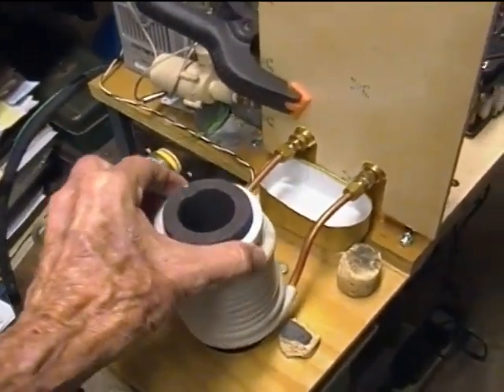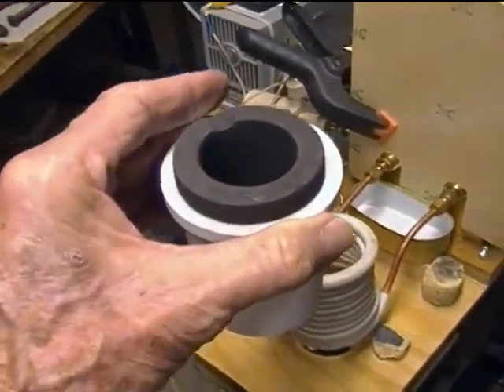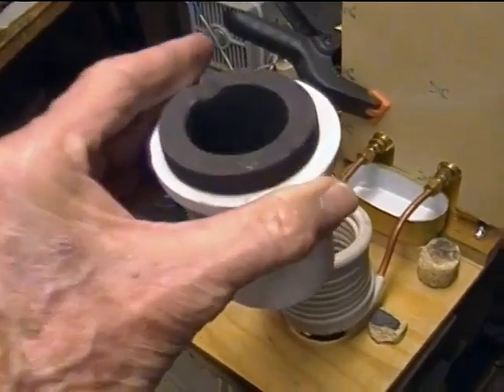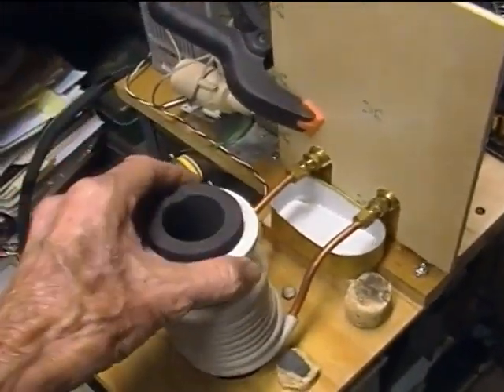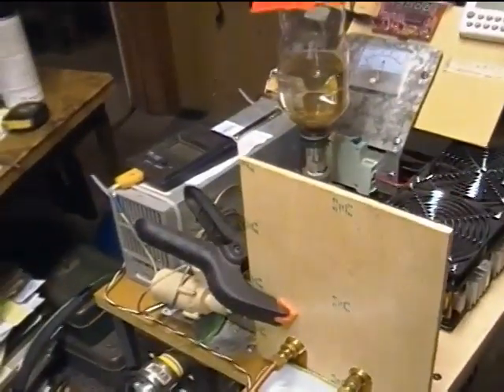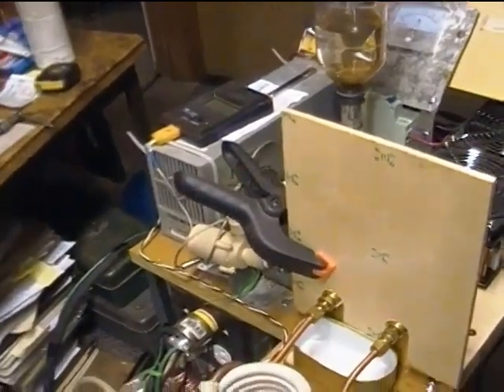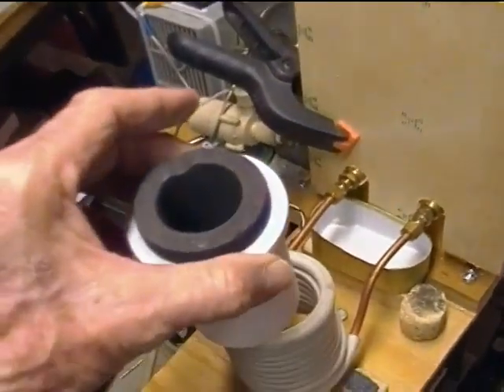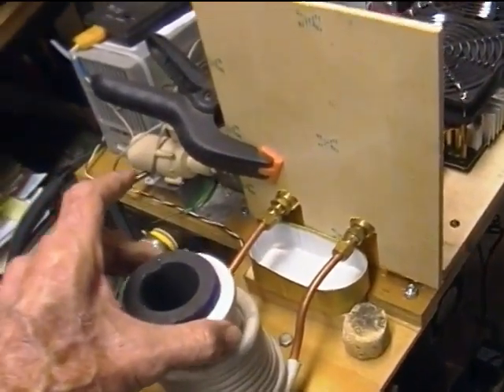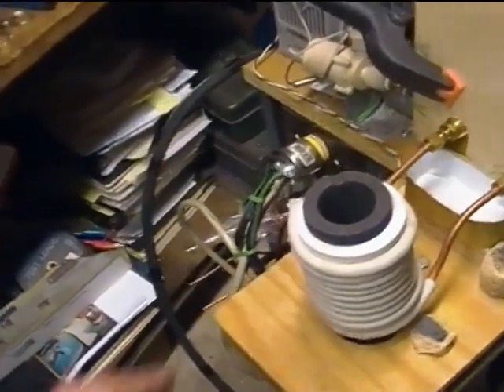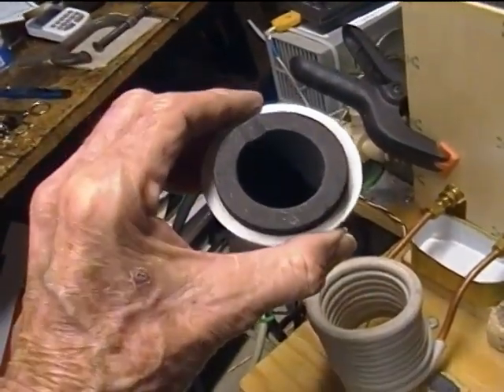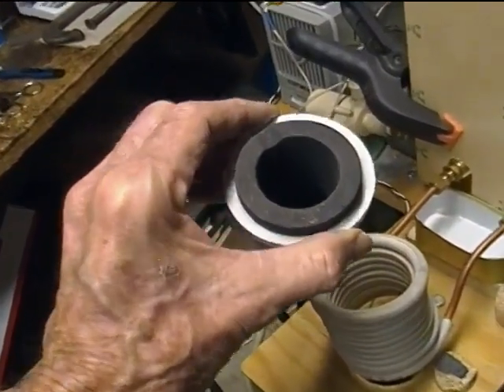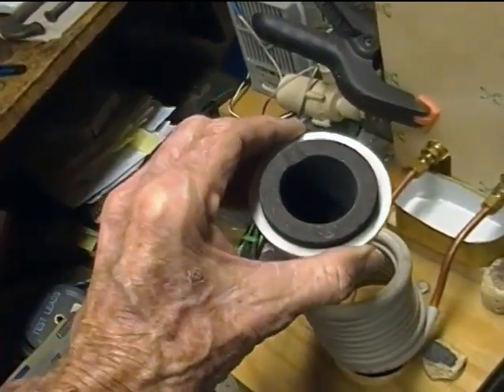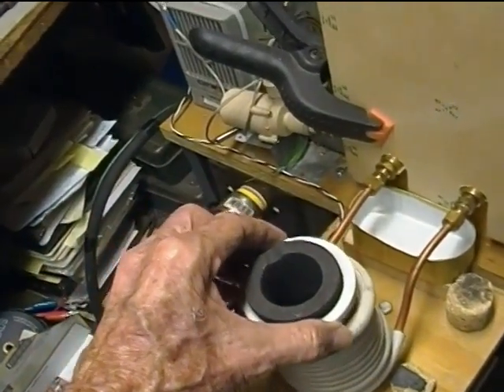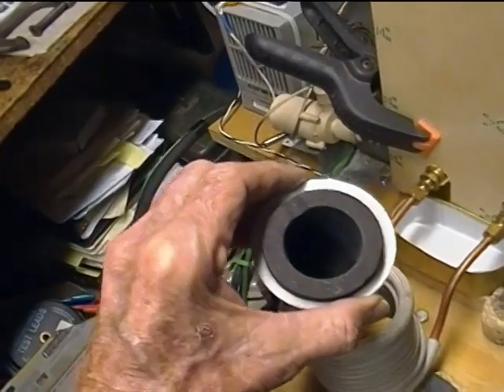However, I suspect that if I have iron bearing material in this graphite crucible and I try to drop it all the way into the work coil, I will clearly be exceeding the current capabilities of the system. So of course I don't want to do that. So what I need is a way to incrementally drop the crucible down into the work coil. So my thinking is that a plain graphite crucible without anything in it and fresh may suck up about 35, 40, maybe even 45 amps even without any metal in it at all.